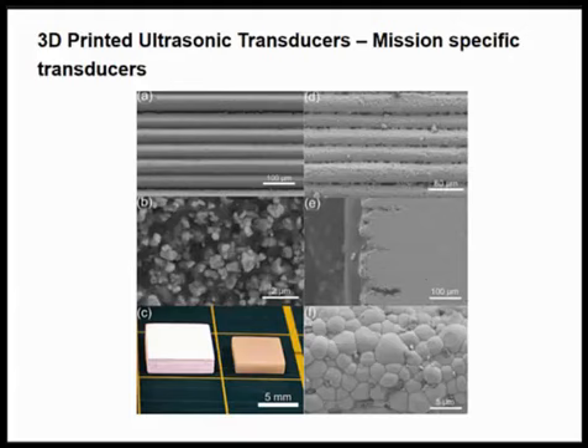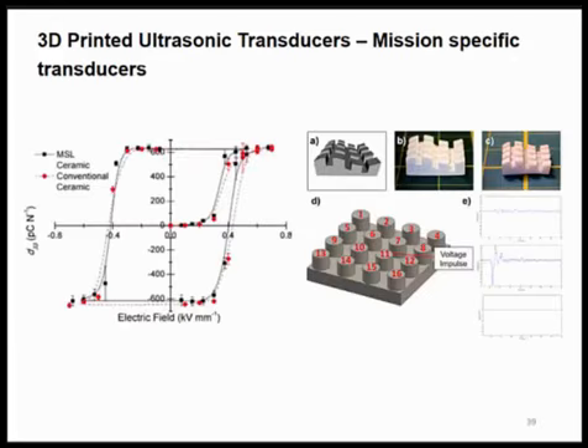And again, there's a perception that 3D printed objects are not as good as the real thing. The density of this 3D printed ceramic after firing is indistinguishable from conventionally produced ceramic. D33, so its piezoelectric coefficient, is identical to conventionally produced ceramic, but we've got control over the structure, which you can't necessarily get easily with a conventional ceramic process.